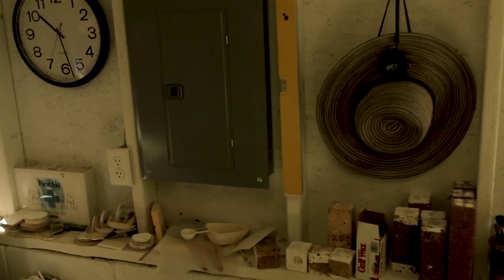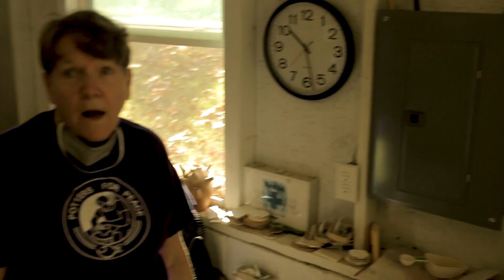So what would happen if you did happen to take them out? It's bad for the kiln. Bad for the kiln, yeah. I've taught various places where we've unloaded kilns when they were really hot because students had to leave. One time I was teaching at John C. Campbell Folk School, and a snowstorm blew up, and they sent everybody home a day early. We were firing pots thinking everyone was leaving on Saturday morning, and suddenly Thursday evening we had to leave. And we took those pots out when they were so hot that when we put them on the table afterwards, there were little burn rings. I was embarrassed. I should have put them on the concrete floor. But it's not good for the kilns.